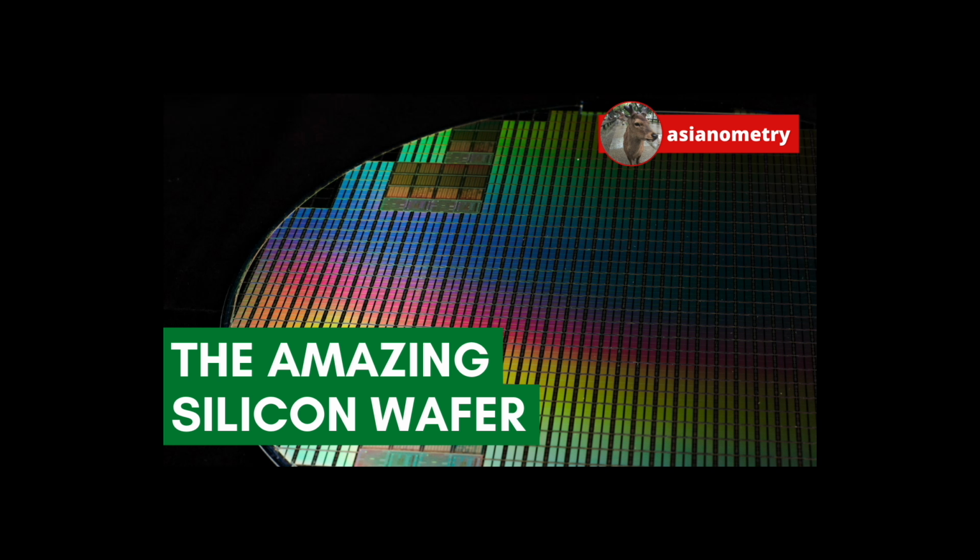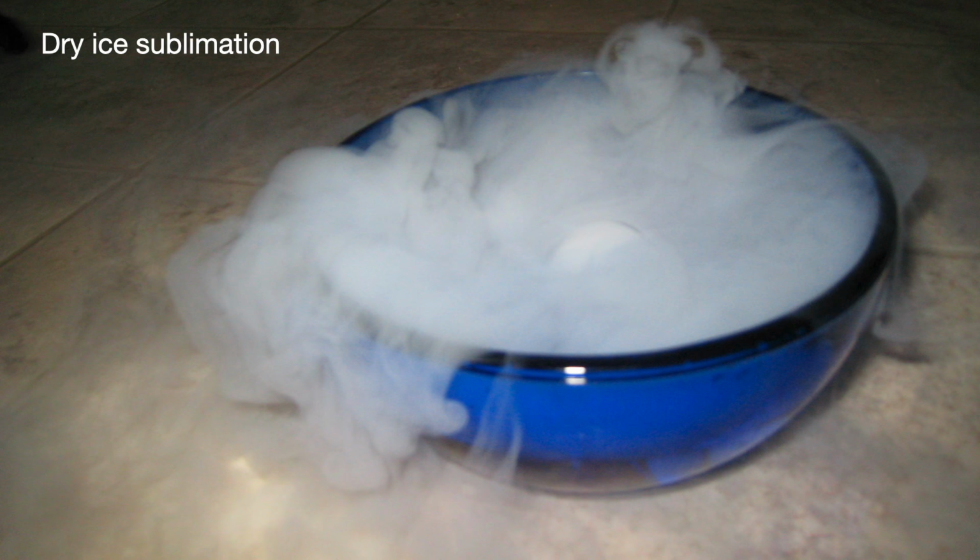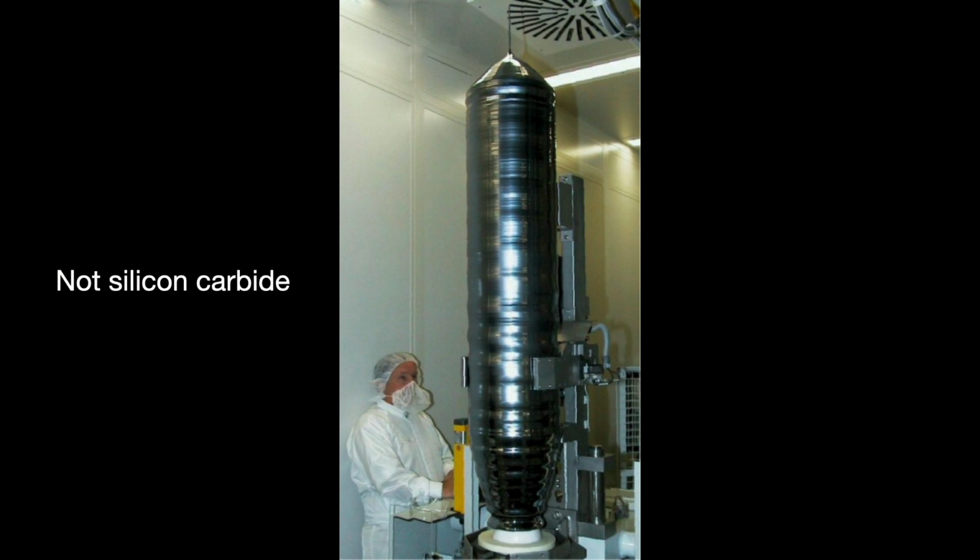The Czochralski method does not work without the liquid silicon melt, but silicon carbide's solid form directly passes into the gaseous form without first turning into a liquid. To use a chemistry phrase, it sublimes before it melts. Because of this, there is no melt, and so silicon carbide wafers cannot be made with our traditional silicon methods. We need to grow our silicon carbide crystals from gas.